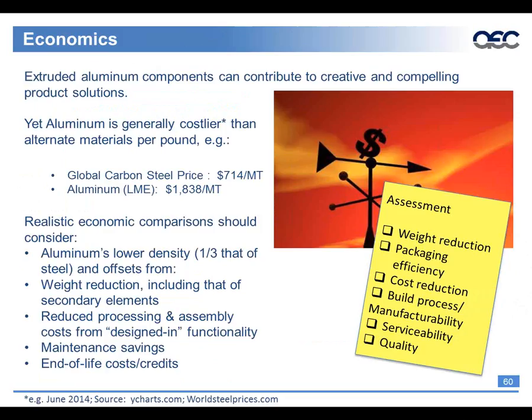But the thing that you've got to keep in mind with aluminum is aluminum has a much lower density. You can do a lot of things with the shape because of the extrusion process. You can design in an awful lot of features that you can't do in steel because you can get aluminum to flow. And then it is very corrosion resistant. Not a lot of treatment has to be done, especially when you get to either corrosive environments, salty environments, coastal. It's very good. And then at the end of life, you have a value that you can harvest out of the aluminum. Not as much value can be harvested out of steel. Next slide.